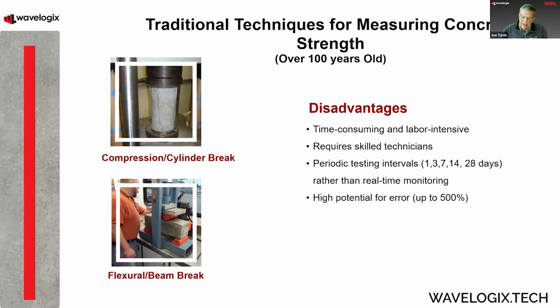Final strength takes about a month for concrete to cure to about 97 to 98% of its total strength. So it's a long time to cure, but early curing is really important for us to do the next operations. So how do we know what that strength is?